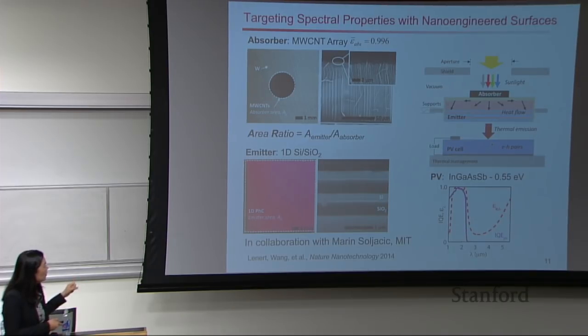So here what I'm showing you is the internal quantum efficiency of the PV cell, which is in purple. And then this is the emissivity based on your emitter structure. You can see here that we're targeting the band gap of the PV cell pretty well. And this way we can aim for really an efficient conversion via this thermal emission process.